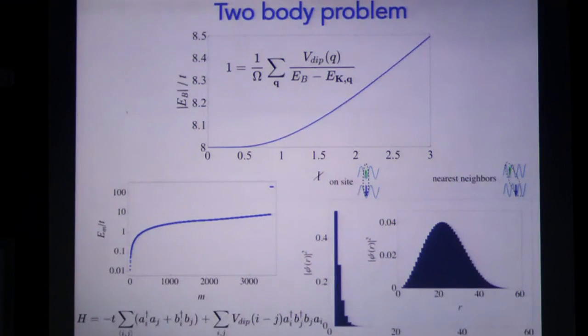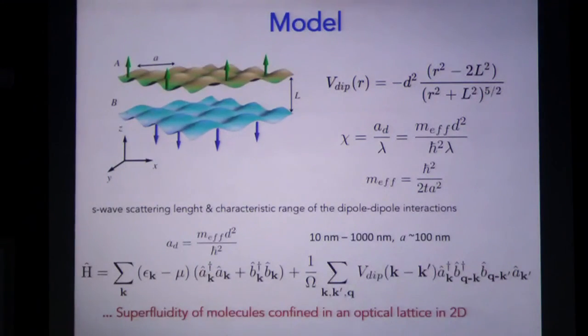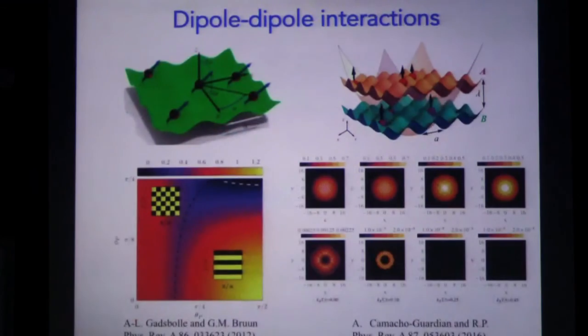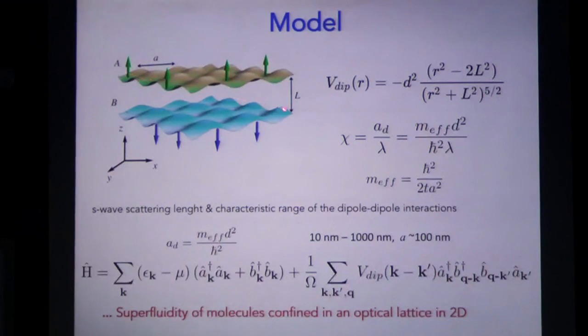So the highest possible energy is when one green arrow is exactly on top of the blue arrow. Why? Because since they have opposite dipole moments, they repel each other when they are at the same site. But if you adjust this separation, then an effective attractive interaction can be established between these Fermi molecules and these Fermi molecules.